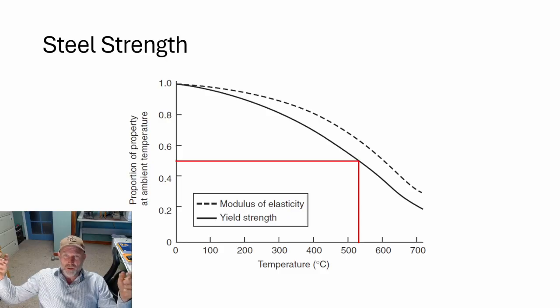Now, you may think it non-intuitive, but a beam can also be modeled as a spring using what's called Hooke's law. If you apply a load or push it or pull it, it's going to spring back. And what happens at elevated temperature is that not only does it lose that springiness, the force that it pushes back, but it loses its overall yield strength. Typically, annealed steel is about 35,000 psi, pounds per square inch, for its yield strength. With different alloying concentrations and work hardening, you can get the steel up substantially more than that. But typical structural steel, for the most part, is about 35,000 psi.